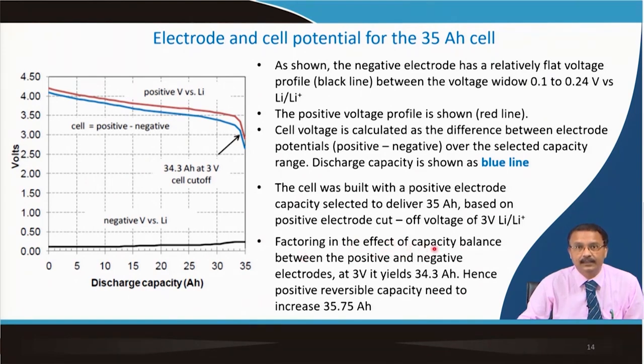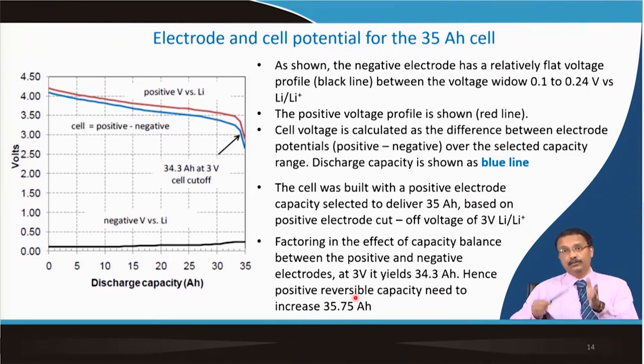So, factor in the capacity balance between positive and negative electrodes at 3 volt, that actually yields you a little bit smaller voltage than this red one. So, a slight change, 34.3 ampere hour. So, the positive reversible capacity needs to be increased to 35.75 ampere hour instead of exactly 35, if you want to have 35 ampere hour in your full cell. Accordingly, you will have to increase the active mass of the positive electrode to get this kind